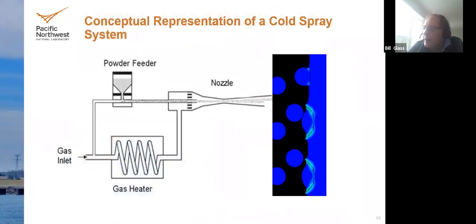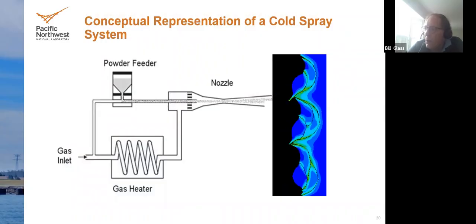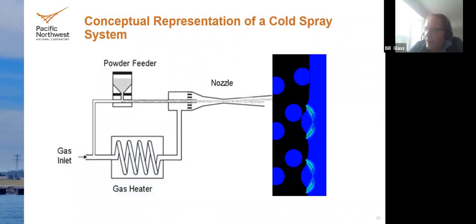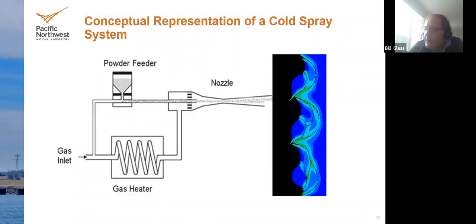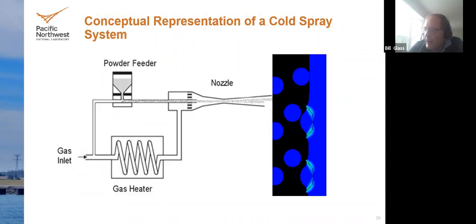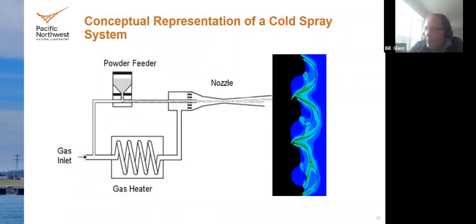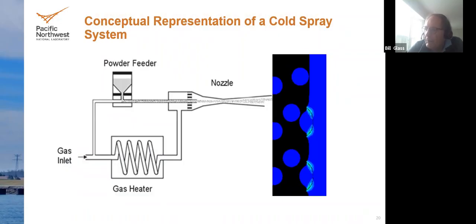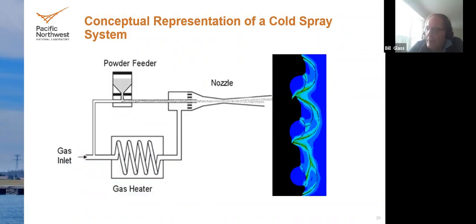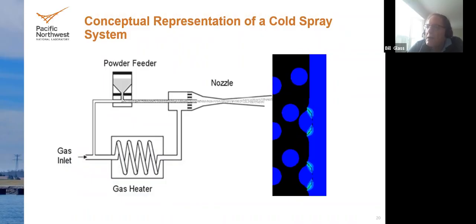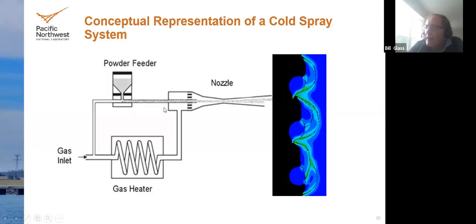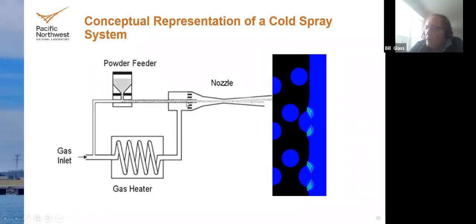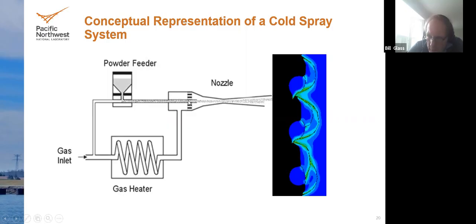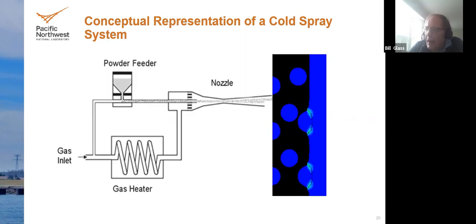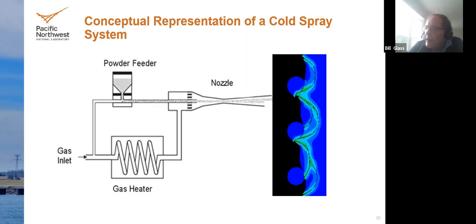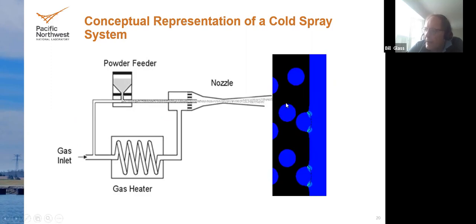We demonstrated that we could use cold spray, and we are in general a fan of cold spray because it offers a number of high potential mitigation and repair technologies, as well as serving as this magnetostrictive material. The cold spray happens by accelerating 10 to 100 micron particles up to about Mach 2 or Mach 3, where they then impact on the material substrate.